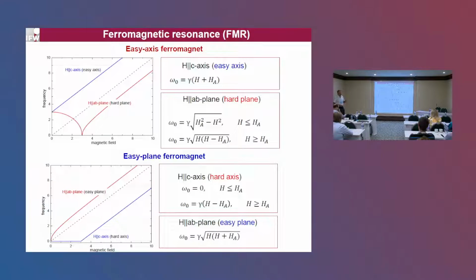If we have an easy plane ferromagnet, so that means the spins prefer to lie in the plane for whatever reason, then these two modes are gapless in zero field. So they develop a Zeeman gap with increase in the field if we apply it for both directions. And this is a very clear-cut difference between the easy axis and easy plane ferromagnet.